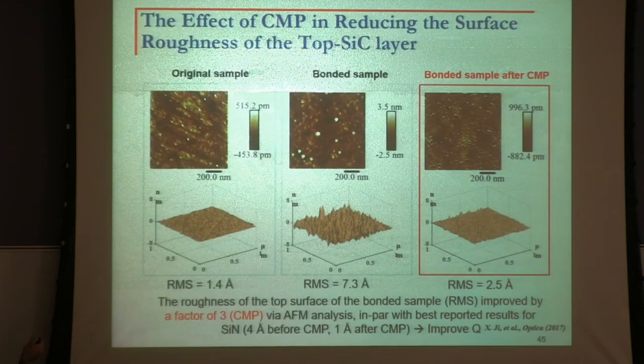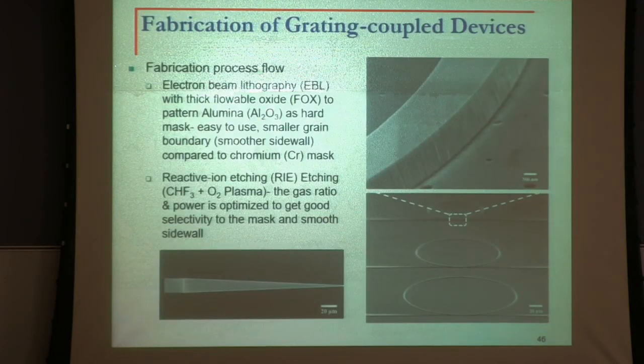So this is the original sample. The top surface of it when we get it is reasonably good. That's the AFM result, and the RMS variation is about 1.4 angstrom because they polish the top surface. The problem is the bottom surface. This is when I bond it and bring the bottom surface up and monitor it with AFM. You can see that. And this is after chemical mechanical polishing. Of course, we did not do this aggressively. If we do that, at least we should get 1.4 angstroms. But that by itself shows that our simple technique can reduce the scattering by a factor of 3.